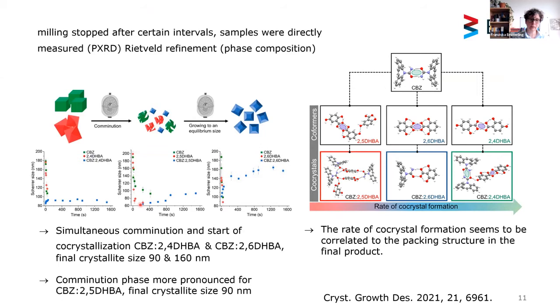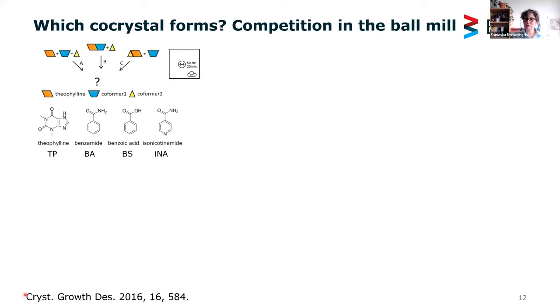These are reactions we can follow ex situ, and there's another example of reactions you can easily perform in ex situ studies, and these are competition reactions. So if you're interested whether a co-crystal will be formed under these conditions, or also which co-crystal might be more stable within a series, these are easy reactions to be carried out, and you can learn a lot about the stability of your compound. You can here see a series of experiments we performed with theophylline and different co-formers.